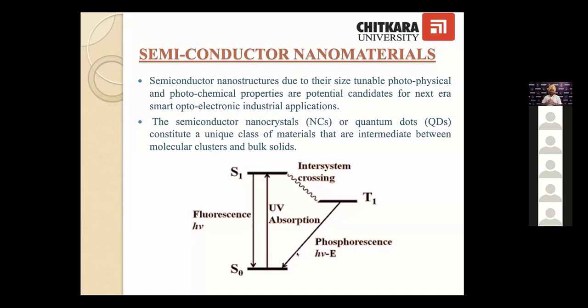Okay, now see the wonder of nanomaterials. You can make the material for two-level application. Now suppose I want to use a nanomaterial for photoluminescence application in optoelectronics. So I have to try that the recombination rate should be higher as compared to the indirect transitions. So what should I do? What I did in my lab, we synthesized nanomaterials. Then we started doping these nanomaterials with certain dopants across the periodic table, rare earth and transition metals. Then we found that at a particular optimum concentration of a particular dopant, the recombination rate is quite high. The material behaves as an efficient photoluminescent material at that particular concentration. So at that concentration, we marked these materials for photoluminescence or optoelectronic device applications.